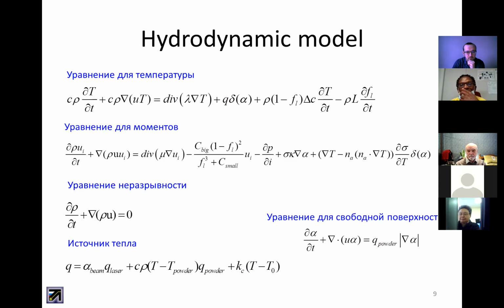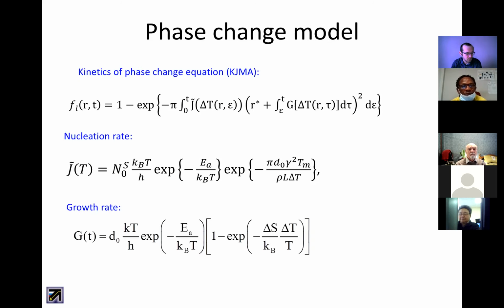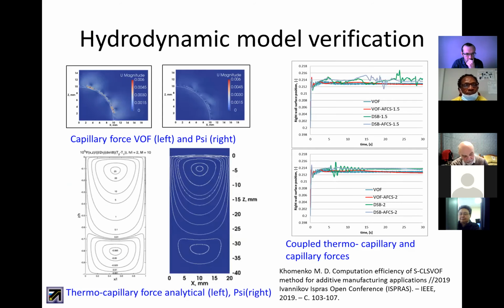It is a coupled model which calculates hydrodynamics, thermal conduction, and the rapid crystallization. And after that, we managed to calculate the average grain size, which is gained at some processing conditions. And we use the model for our investigation of laser metal deposition.